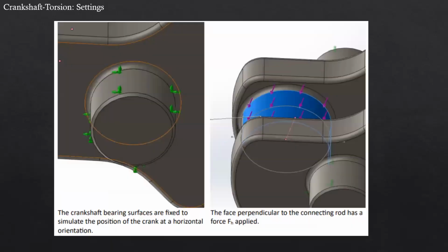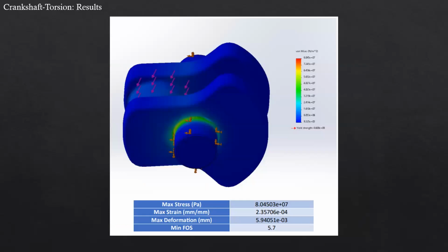have lower costs. Moving on to torsion, we ended up finding that the angle for the connecting rod of 15.069 degrees was applicable here. So we applied that force in that direction. And then these were the fixturings that we did. With the torsion results, we end up with a factor of safety of 5.7, which means that we will not be dealing with torsion issues with our crankshaft.